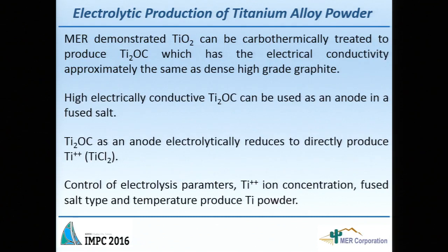So the innovation that we came up with many years ago is to do this carbothermic reduction step combined with electrolysis. So here we take TiO2 plus carbon, at high temperature, under controlled atmosphere with some vacuum, and you produce Ti2OC, titanium oxycarbide, right? And it turned out that titanium oxycarbide is fairly highly conductive. It's almost as conductive as high quality graphite. It is the color of iron sulfide. It's a gold color.